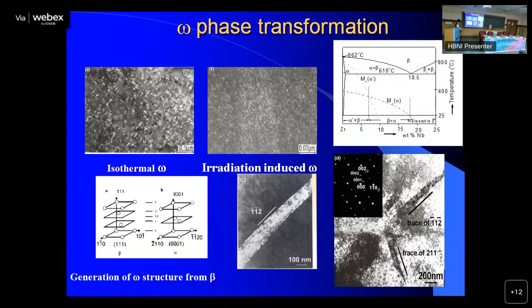Omega forms from the beta phase. This is the beta lattice. By collapse of these planes, you have this, this is the omega structure, which is a hexagonal structure, not hexagonal close pack. Beta phase is BCC. BCC to omega transformation takes place in the beta, provided the composition is right. That is, if the composition is in that range, beta phase, then it will transform to omega.